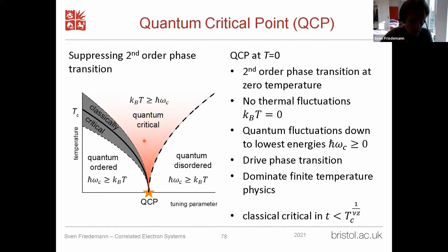That means quantum fluctuations between the ordered and disordered state can occur in this regime, and on top of that, thermal fluctuations can occur. This is actually not just a line, because that same argument holds as we go slightly to the right. Yes, here the balance in terms of energy is technically favorable for quantum disordered. However, it's only a little bit favored in that direction, and given that the temperature is finite, thermal fluctuations are finite. Hence, we can go some distance to the right, where the thermal fluctuations are still going to be larger than the energy difference between the ordered and disordered state. And the same holds if we go to the left here. And that's the reason why we've got this fan of a region where quantum fluctuations between the ordered and disordered state are present, and thermal fluctuations are present too. So they can both work there.